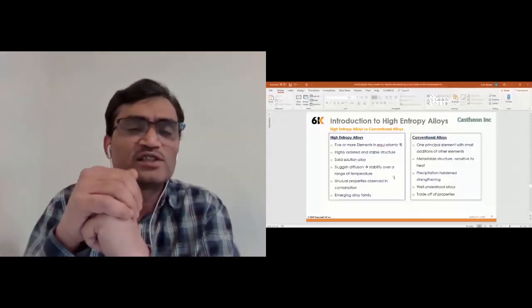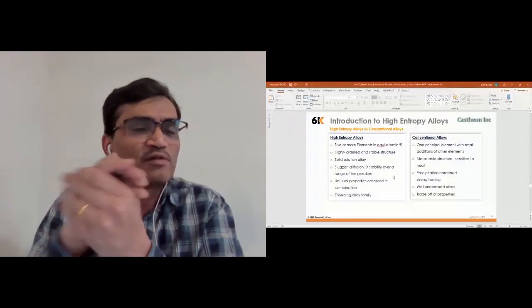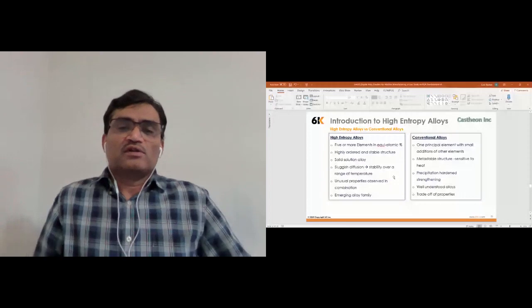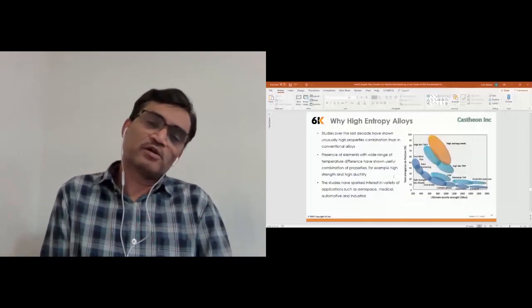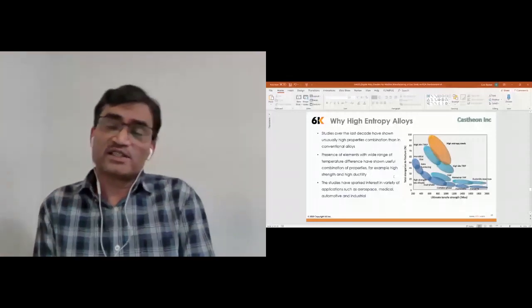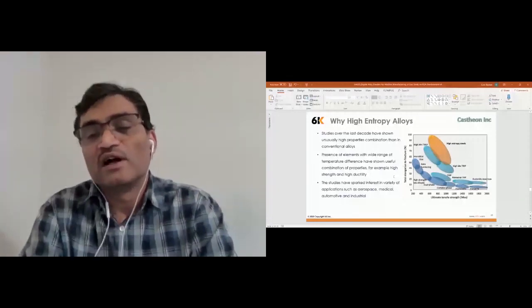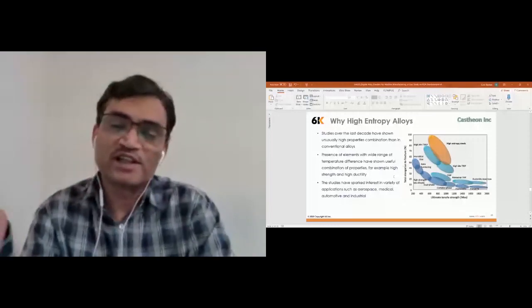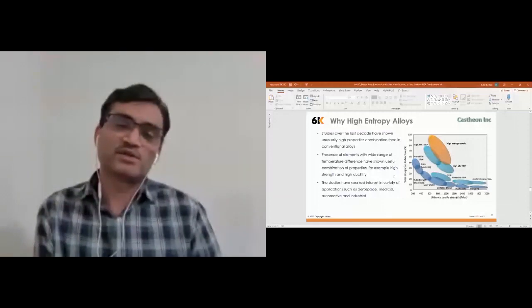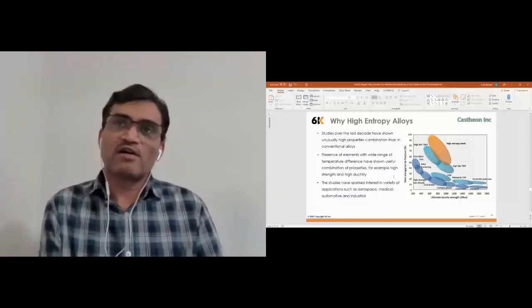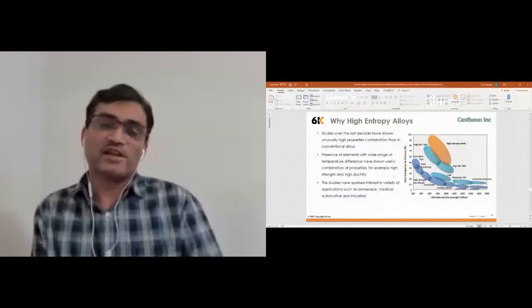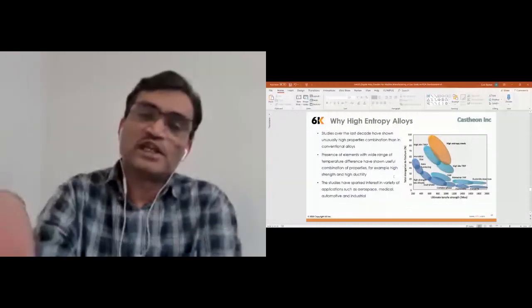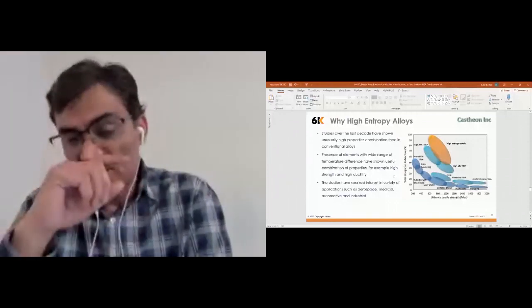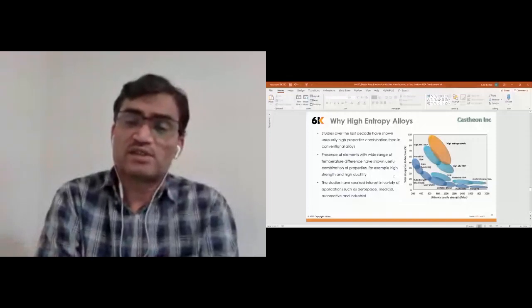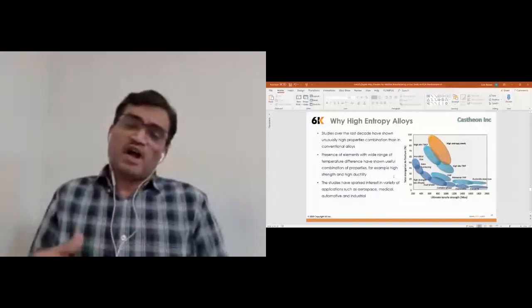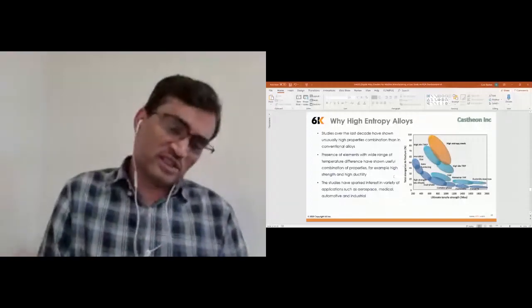And again, in studies, it is observed that there is a combination of properties. In this picture, you can see the combination of properties, strength and ductility. Normally in conventional alloys, take martensitic steels, these are very high strength steels, but the ductility is very low. So it is like a trade-off of properties. You want high strength and ductility, but if you see in the orange, there is a region of high entropy alloys where you can have a combination of high strength and high elongation in the same alloy.